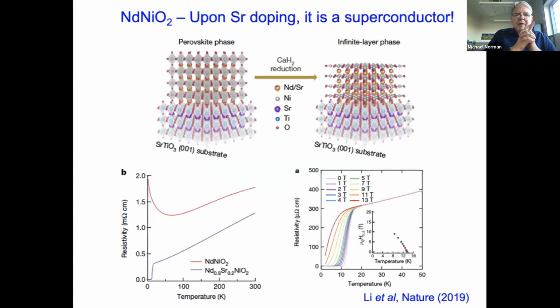So the surprising thing is, of course, we all knew about these things for a long time. In fact, if you go to Mike Hayward's thesis, he actually doped these 112 nickelates. But it took Harold's great discovery in 2019 to realize that these materials were actually superconducting. And superconductivity was not impressive, maybe around Tc of 15 Kelvin, but people have been able to push it up higher by pressure and other tricks, just like people had done in cuprates.